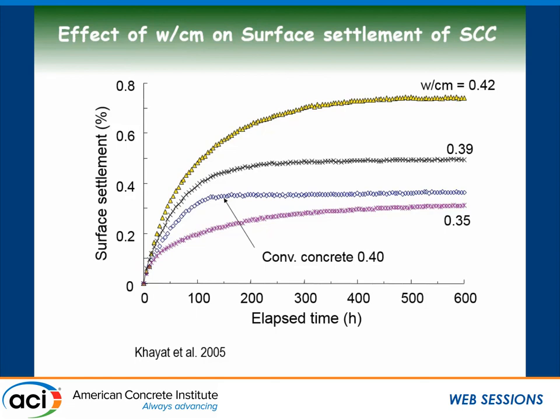So you're picking up on the, and Jason, this is based on a lot of data points. There's probably more than 100 data points on flowable concrete SCC consistencies. You're looking at what happens at the slope between 25 and 30 minutes, and how that slope is lower, higher and higher, and what happens with the maximum settlements. There's a good correlation. I forgot the R-square and stuff. I can check it out and send you the reference. But there's a good correlation. That was part of the NCHRP study that we did with a lot of concretes.